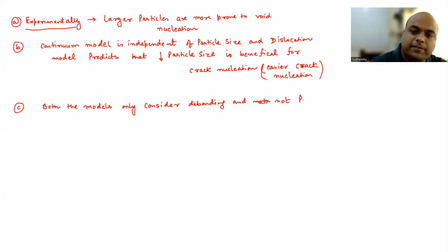Now the third point is that both the models only consider debonding and not particle fracture. So in both the models, we talked about the interfacial stress and they consider only debonding, not the particle fracture. Okay.